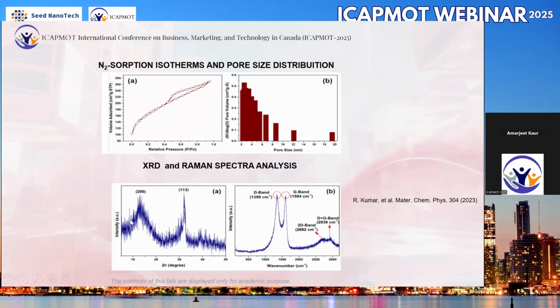And you can see that XRD shows a typical amorphous distribution. This is the 200 plane, and then we have a sharp peak at 32 degrees, where the d spacing lies around 2.8 angstrom. Both the peaks show that there is a highly disordered state.